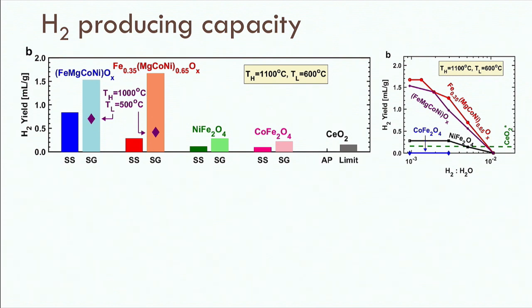And the material that we have found, this iron, magnesium, cobalt, nickel oxide, it's much better. This is 1100. And we said, can we try 1000 degrees where the other materials don't even work at all? And we find that indeed you can get this material to work to produce hydrogen at 1000 degrees Celsius. And we're trying to go even lower.